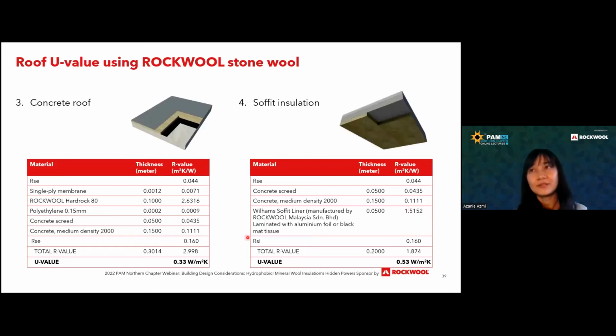Flat roof, concrete flat roof, also 100 mm. Well, this actually depends. I just want to show that because actually 50 mm you already can comply with 0.6, but sometimes you need a thicker insulation to comply because it's subject to certain mechanical requirements.